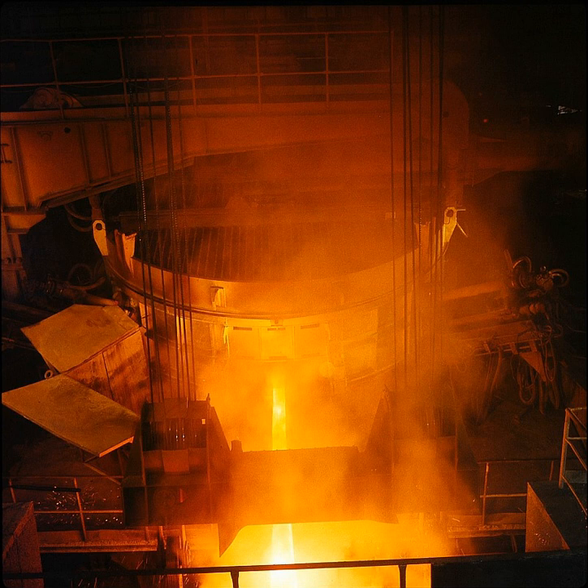As the refractories are often made from calcined carbonates, they are extremely susceptible to hydration from water, so any suspected leaks from water-cooled components are treated extremely seriously, beyond the immediate concern of potential steam explosions. Excessive refractory wear can lead to breakouts, where the liquid metal and slag penetrate the refractory and furnace shell and escape into the surrounding areas.